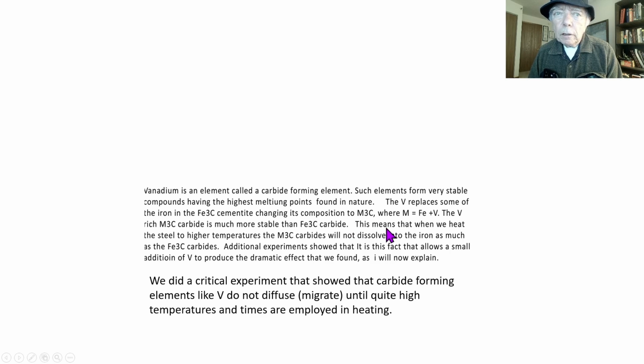Now, when we heat a steel to a high temperature, mixtures of M3C will not dissolve into the iron as much as the pure Fe3C carbides. This interesting fact explains why later experiments show this. Just a tiny bit of vanadium produces the huge effect that we found. Now I want to show you on the next couple of slides what these carbides do in steels.